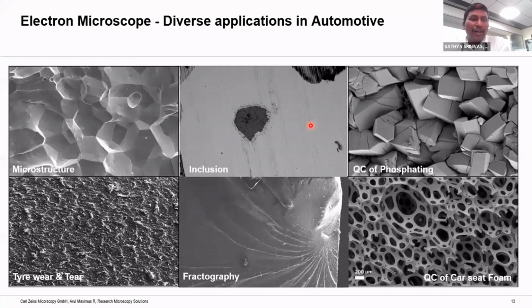A few more applications in the automobile industry: the surface features, inclusions, phosphate coating, where you can understand the grain size of the grains, and in failure analysis, the initiation of the crack, how exactly it penetrates, and the direction of these cracks through the features. If you go for a higher magnification, you can understand the microstructures, right?